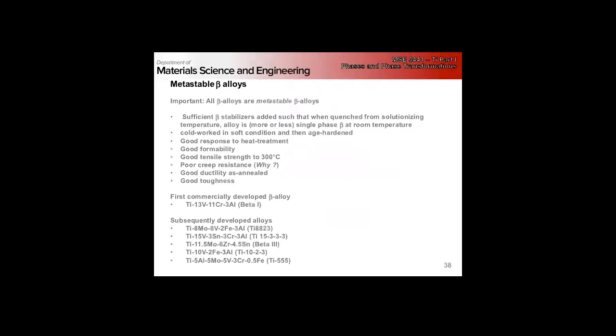The key thing is that they just have a higher beta stabilizer content, so that when we're rapidly quenched from above the transus, you end up with a structure that is more or less still single phase beta, whereas the alpha beta groups of alloys will begin to transform on quenching, right? So with the rapid quench from above the transus, you get the nucleation and growth of grain boundary alpha and Widmanstätten alpha. In the beta alloys, we have enough stabilizer that when you come down, you're basically all still in the beta phase, right? The key thing to remember is that all beta alloys are essentially metastable, right?